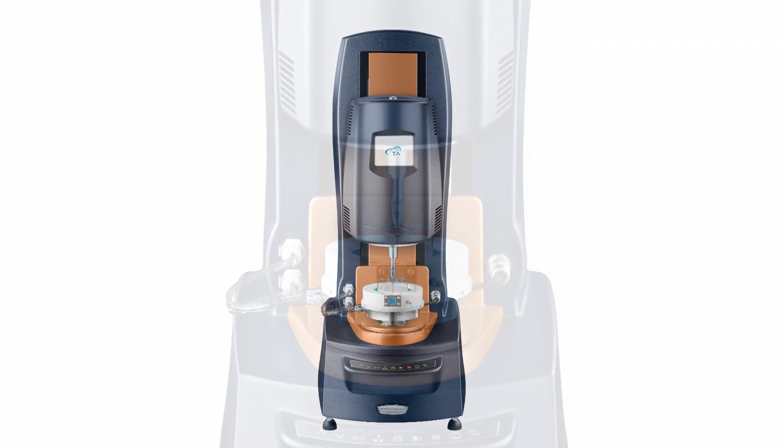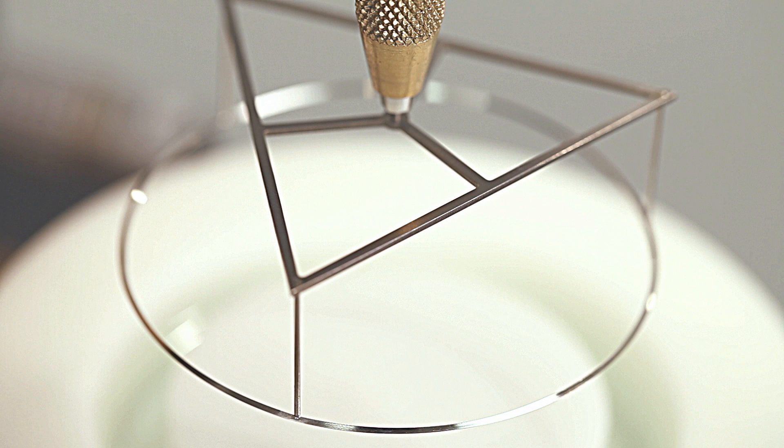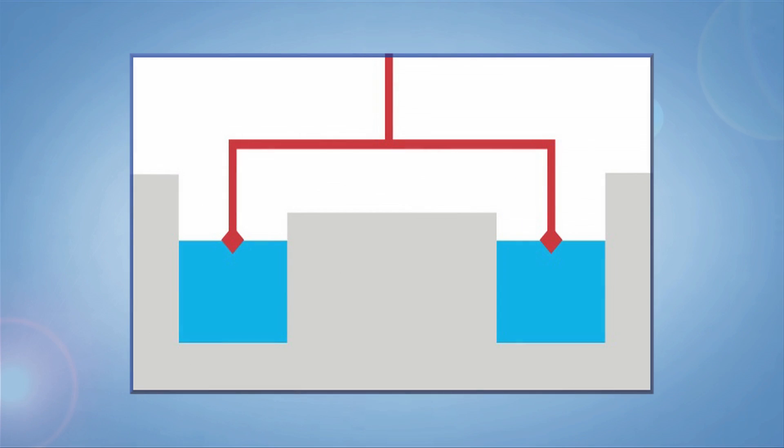The double wall ring is an advanced geometry designed for measuring viscoelastic properties of the interface of two immiscible liquids or the interface of a liquid with air. The ring's square edge shape pins the interface in place, making it the only system that can make quantitative interfacial measurements.